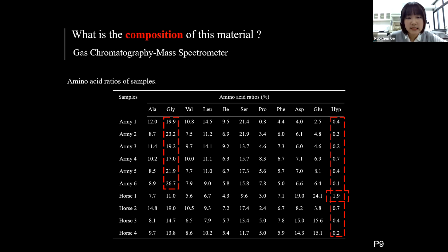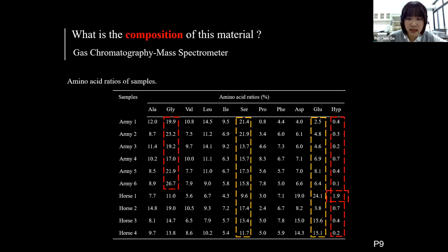samples. Additionally, the glutamic acid ratios in all samples are high, over 10%, and similar to that of the eggs. The ratios of serine and aspartic acid are high, which is an exclusive characteristic in eggs. All the results above lead to the conclusion that the organic matter in this adhesive material is a mixture of animal glue and eggs. This is also a common binder in ancient China.